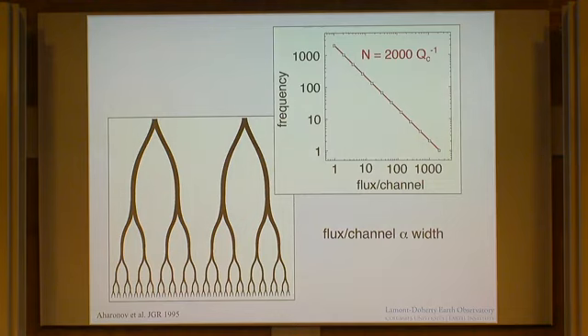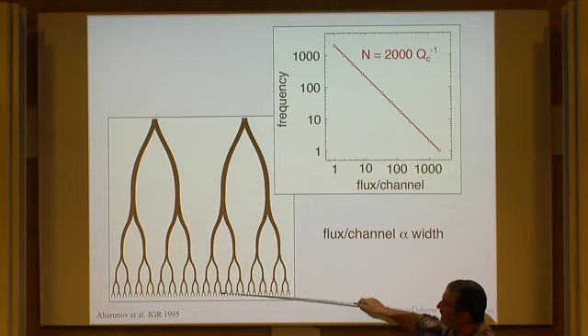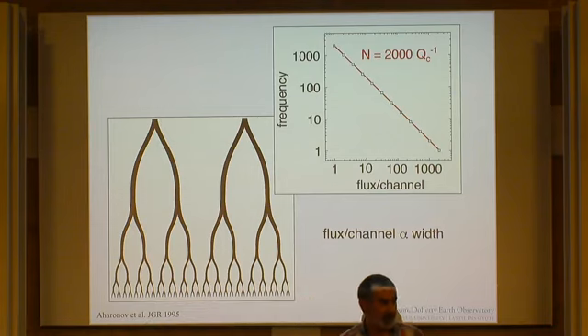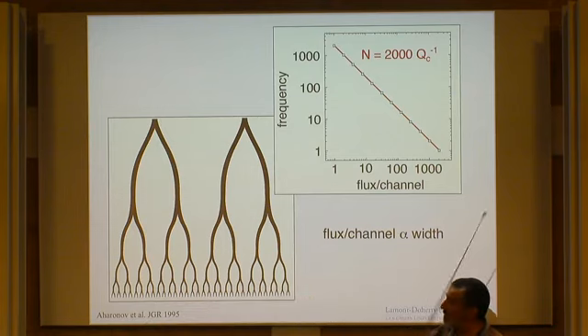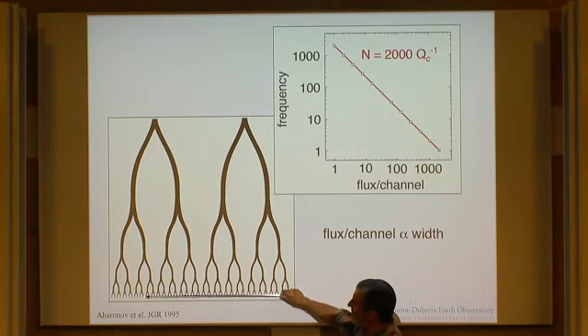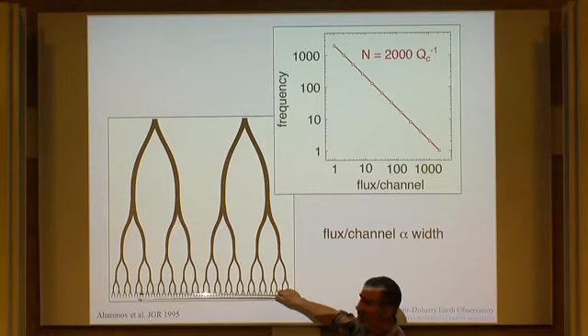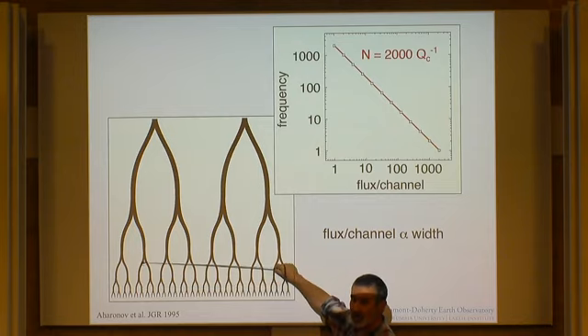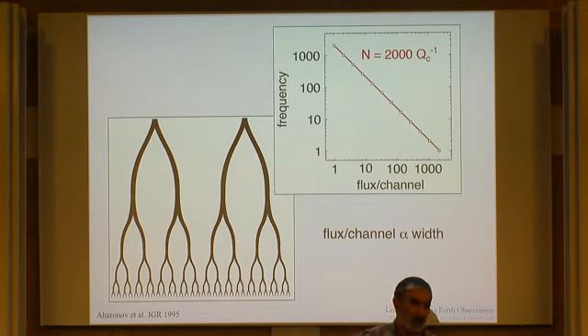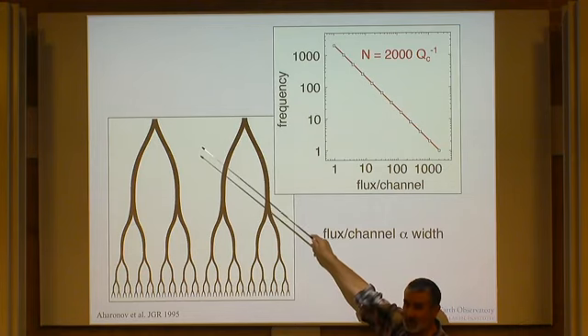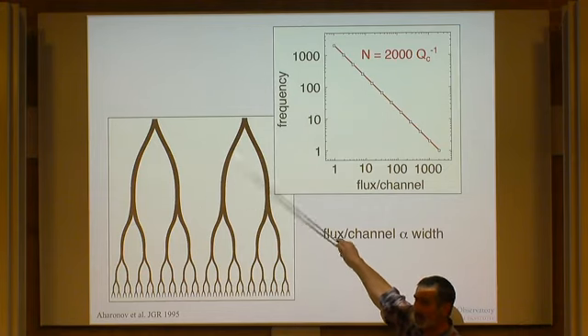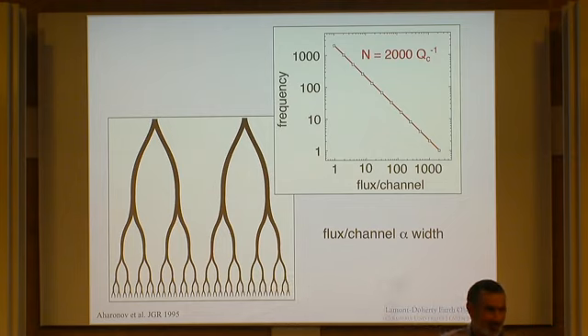And from a theoretical point of view, the wavelength of the dissolution instability is determined by a few things, but one of them is the melt velocity. And so we had this notion that once I get a channel network at the smallest scale, the melt velocity has gone up. And so the wavelength of the instability should rise, and so we'll have a larger one. When we drew this, we didn't really know whether this dimension should be space or time or what, but we just wanted to, I don't know, draw a picture.